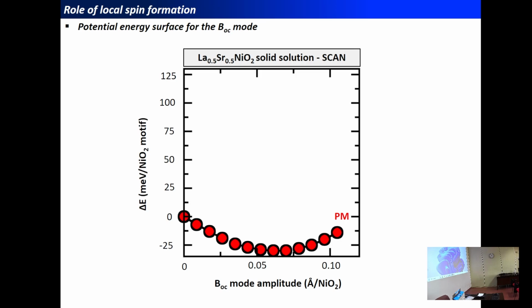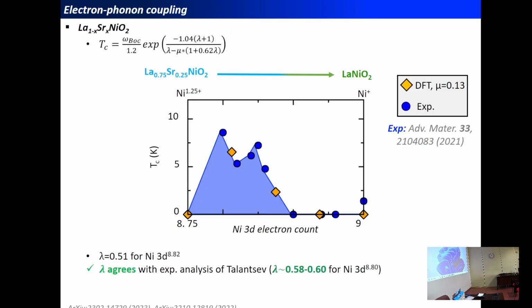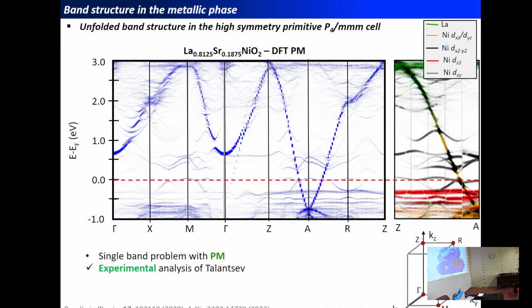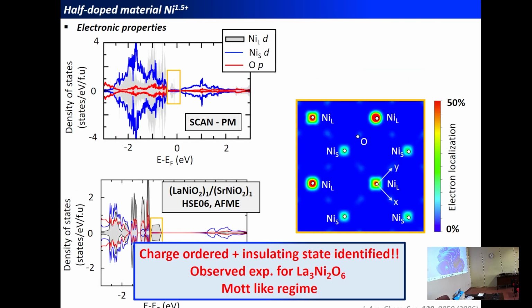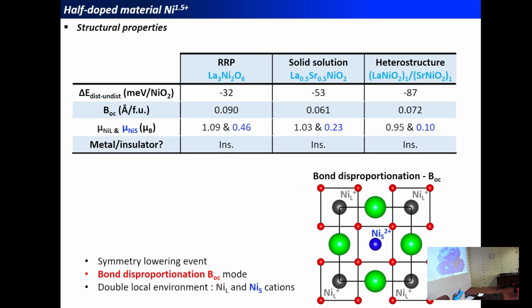In my simulations, you can check the spin ordering, so the spin moment you have on each type of nickel cation, and effectively, what we see there is the asymmetry in the table. We see the asymmetry of the two types of nickel cations. So for sure, it's not exactly zero there, because with the paramagnetic order, each nickel cation has a different potential. So sometimes it has 4 spin up and 2 spin down, so it does change its spin polarization a little bit, but it's close to zero. So clearly we see the asymmetry, 1, 0. With these ground states, I also observe the charge ordering by building the Wannier functions associated with the insulating state. And clearly, we can only build Wannier functions on this side, nothing here. So clearly, we can see it.